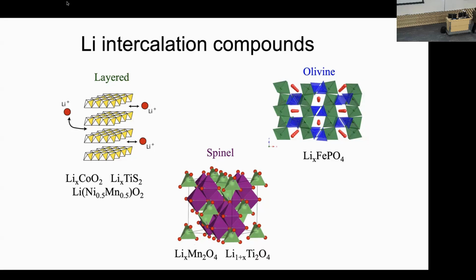This is lithium iron phosphate. It's getting traction in the Tesla batteries. They have one-dimensional tunnels for the lithium ions. So when you insert and remove lithium, they go down those tunnels. You can pull them back out, create vacancies, and so forth. And because of transition metal oxides, their electronic structure is very rich. So when you put lithium in, you're actually oxidizing or reducing the transition metals.